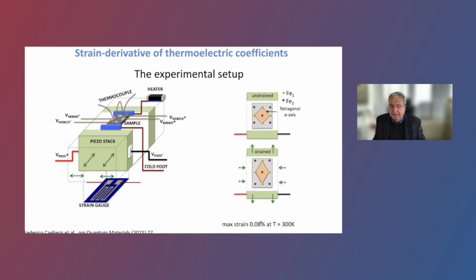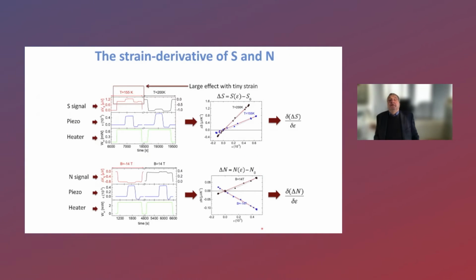Again, the maximal strain which we can apply here is very, very small. It's below 0.1%. Nevertheless, we can measure changes of the thermal power, and that's just shown here. That's a typical experiment. What we do here: we switch on the heater, get a temperature gradient. Then we switch on this piezo, apply a strain. From this temperature gradient, we get a voltage here. This is the Seebeck voltage.